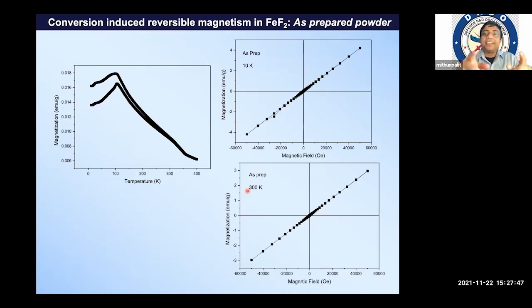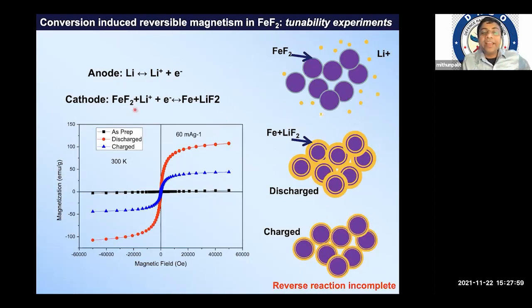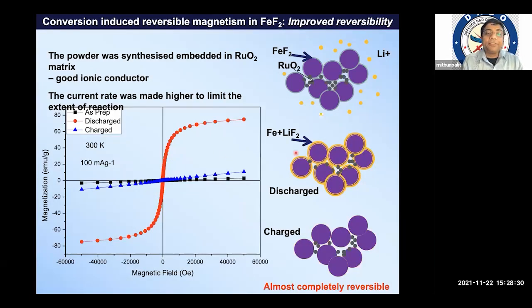The other concept we have utilized: we have taken some iron fluoride. If you see the magnetization plot, it is passing through the origin. So that indicates this is a paramagnetic material. And when we made this paramagnetic material react with lithium ion, it reduces the FeF2 to iron. You can see the orange layer around this FeF2 particle. And when the iron forms, the material becomes ferromagnetic from paramagnetic. Then when you do the reverse reaction by reversing the potential, again that iron is converted back to FeF2. However, in our initial experimentation we were not 100% successful, but we optimized our reaction, processing, charging and lithiation conditions, and then we could achieve a perfect paramagnetic to ferromagnetic and back to paramagnetic.